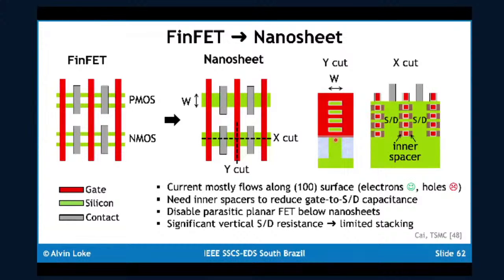And the other thing also to keep in mind is that for current to travel from the source drain contacts down to the very bottom nanosheet, the series resistance of the source drain is very high. And so there is a limit to how much we can keep stacking these devices.